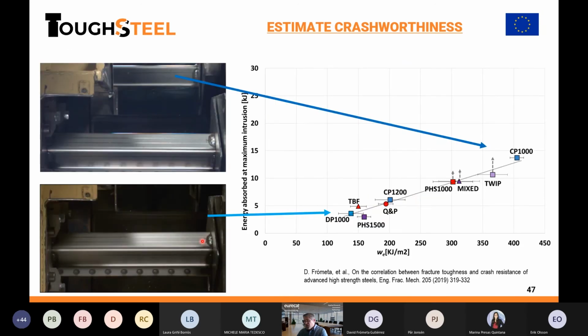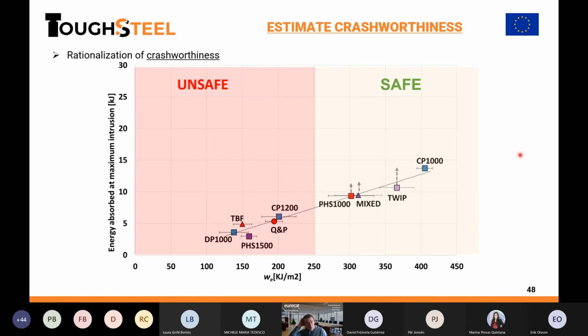Okay. Here it shows not so high energy absorption behavior associated with low fracture toughness. And on the contrary, complex phase steel shows a nice buckling, nice folding behavior that gives a high energy absorption, also associated with a high fracture toughness. Based on these results, we can make a map to rationalize crashworthiness. This is almost arbitrary, but our expertise is putting the limit at this point, that after this value the materials are safe or have high crash resistance, and below this value we have not so good.